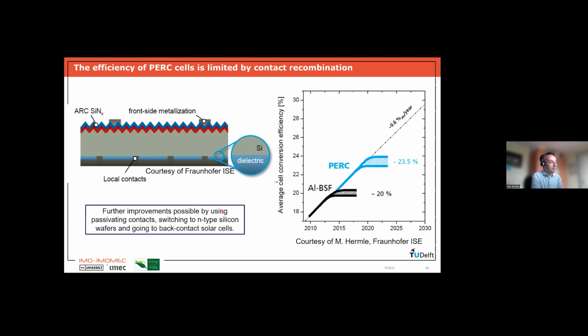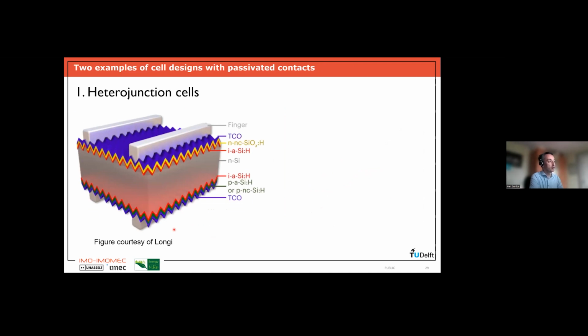There are different things there. The most important part is we should go to passivating contacts. So these are contacts where actually we have nowhere direct contact between the silicon and the metal. Also, we probably have to switch from P-type wafers, which are typically used for both aluminium BSF and PERC, to N-type silicon wafers, because N-type silicon wafers typically have higher minority carrier lifetime, so they are better suited for the very high efficiency devices. And so I will show you now two examples that are being heavily investigated in silicon photovoltaics of passivated contact cells. The first one is the so-called heterojunction cell.